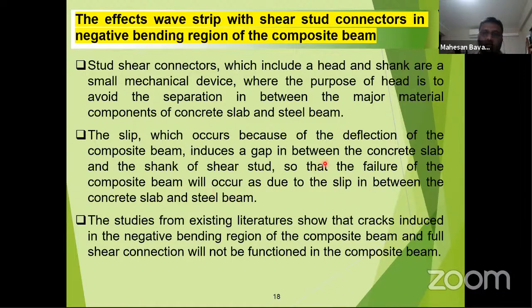In the vertical load, there will be a gap between the shear connectors and the concrete slab. This is due to the slip. This axial tension will also induce excessive slip, so the gap will be more. So we are introducing the wave strip to resist this, to allow the composite beam to reach a higher ultimate state. The studies from existing literature show that cracks are induced in the negative bending region of the composite beam, and full shear connection will not function in the composite beam.